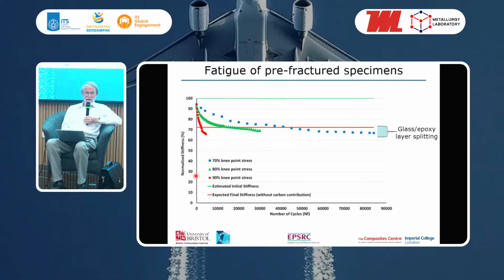So if you look here, you'll see that there's a reduction in the stiffness due to this fatigue, but depending on the load level, it's quite slow. So these ones here, at 70% of the knee point, it's going up to about 10,000 cycles before it starts to drop, and it's going up to about 30,000 before it reaches the full delamination stage. If we do it at 80%, then it goes quicker, or at 90%, it goes after just a few thousand cycles.